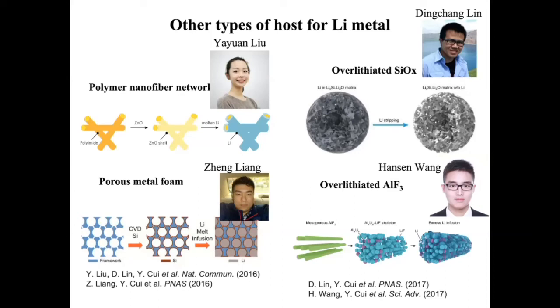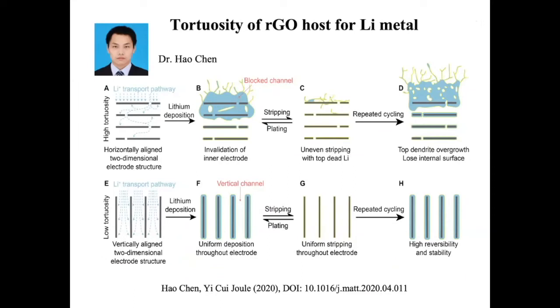And over the years, not only my group, certainly the whole research field has already developed a number of hosts that look very promising to promote the stable cycling of lithium metal. Now we ask one more question. With all these hosts right there, fundamentally thinking about lithium transport, what else do we need to take care of? Let me use graphene oxide as an example about the tortuosity of lithium metal foil, lithium metal hosts. We know tortuosity has been used for your transition metal oxide cathode or graphite anode. Tortuosity is important. For lithium metal, maybe it's even more important.